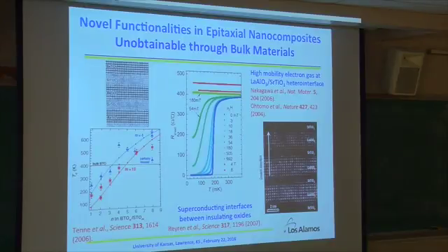Another one, superlattices. Look at this one: strontium titanate and barium titanate in a superlattice structure. This is actually from Cornell University, so that's not our work. I just give you some introduction here. Strontium titanate is not ferroelectric, but barium titanate is. When they put these two together in a superlattice structure, due to the strain effect and tetragonal distortion, you can change strontium titanate to ferroelectric, even above room temperature. You really totally change the functionality, the intrinsic property of the material.